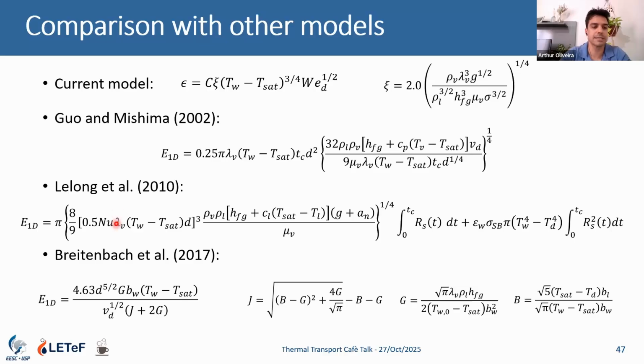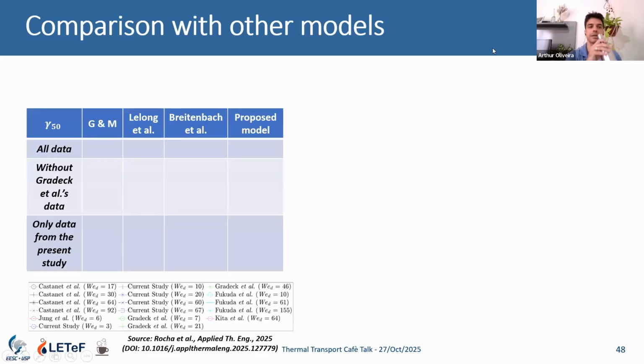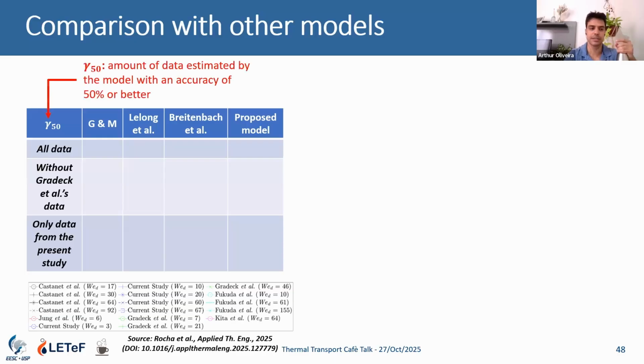We have Mishima's, Lelong and colleagues', Breitenbach and colleagues' models, where they had very elaborate models, and we tried to compare with the collected data. For this comparison, we used the parameter gamma 50, which is how much data, in percentage, is estimated correctly by the model with an accuracy of 50% or better.